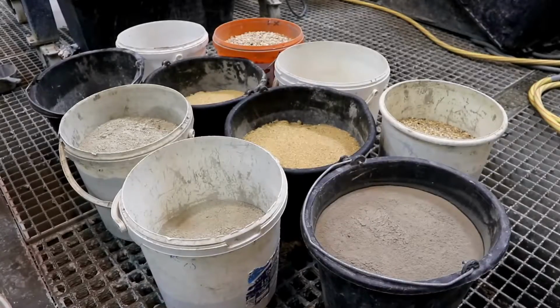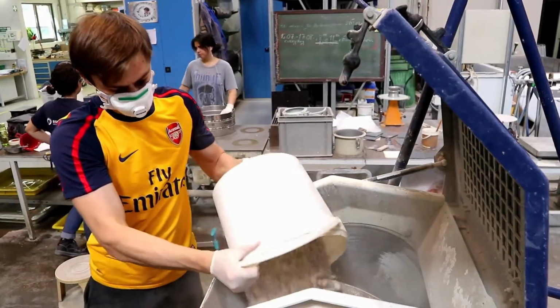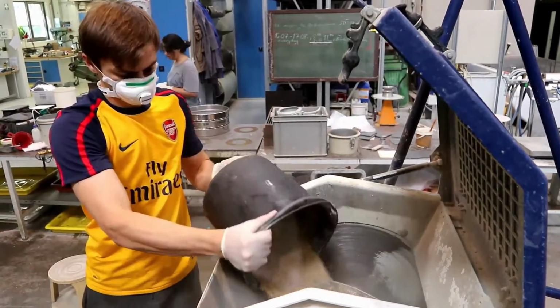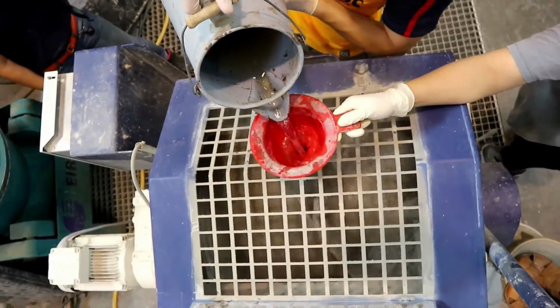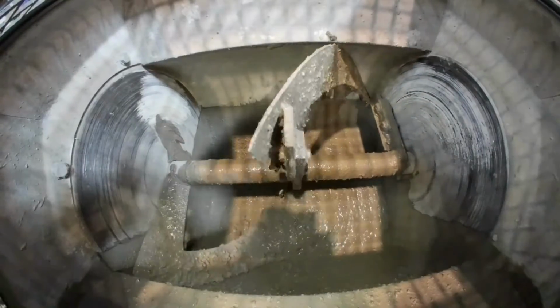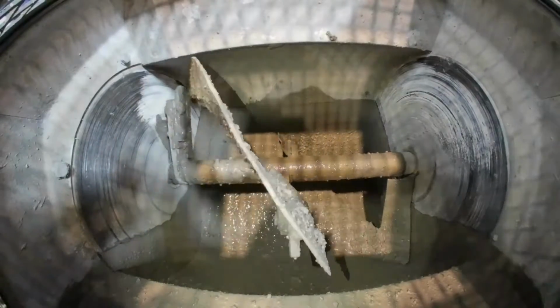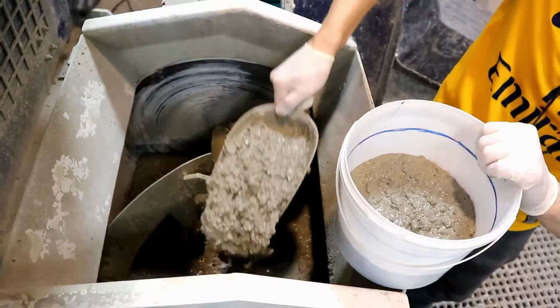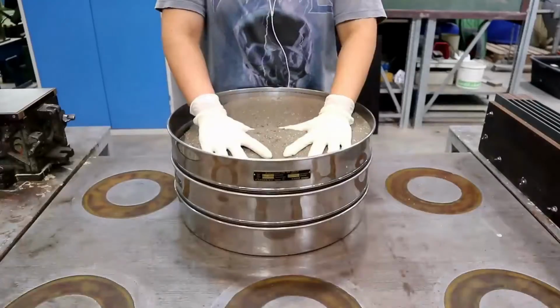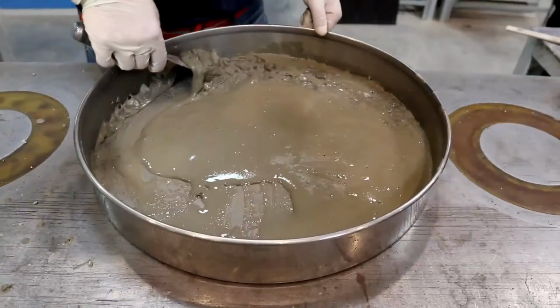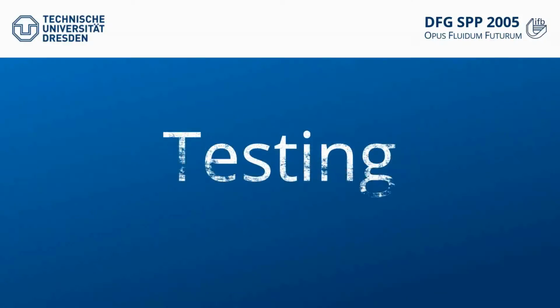It all begins with materials and device preparation. Next, the dry components are mixed in the mixer for a few minutes. Then the solution of water and superplasticizer is added to the dry components. By the end of mixing, 4 liters of concrete is discharged to obtain the constitutive mortar.